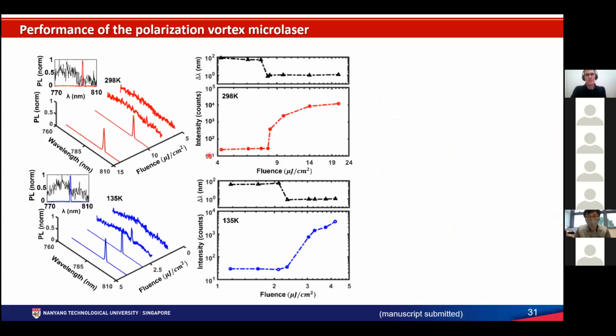Then we pumped the metasurface with a femtosecond laser to test the lasing capability of the metasurface. And indeed, we observed a lasing light line with a typical S shape. In the first case, at room temperature, we observed laser emission with a threshold of about 8 microjoule per centimeter squared, and the collapse of the line width.